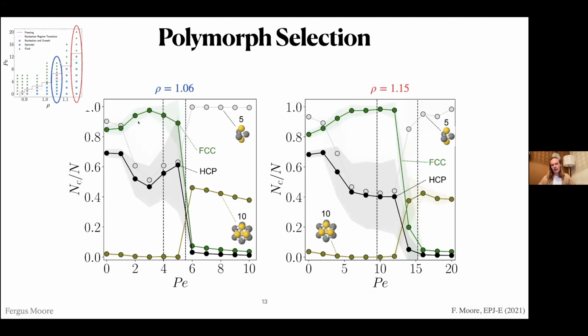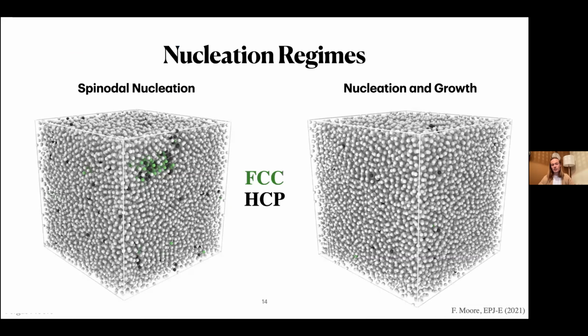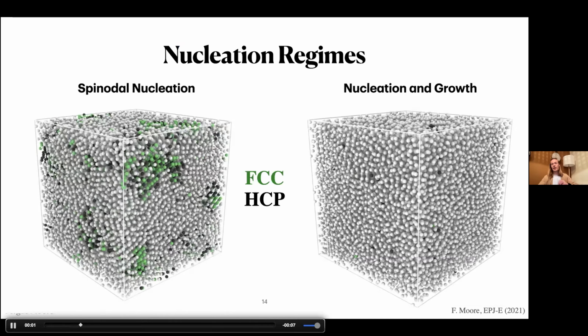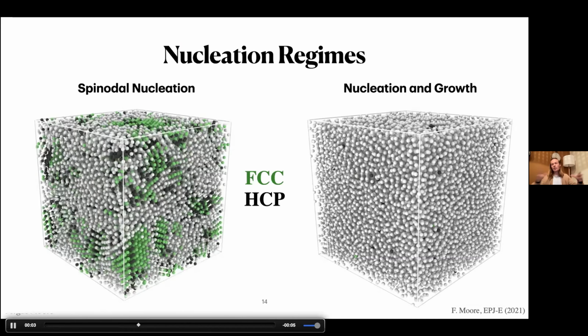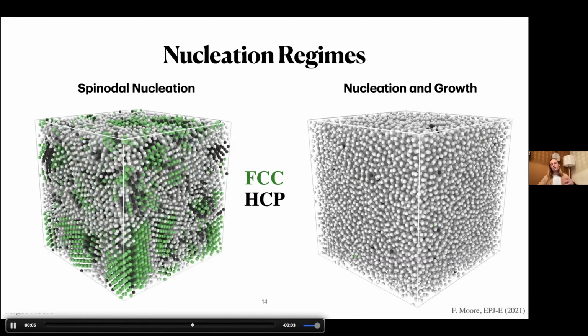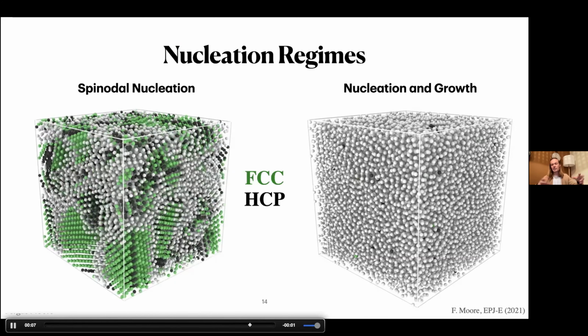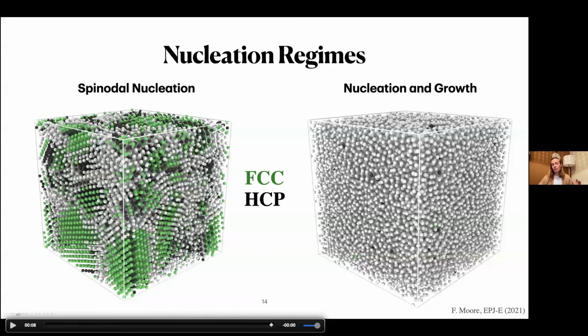So to the left of this line, we're going to be looking at spinodal nucleation. And in between here, when you have a slightly different polymorph selection, we have nucleation and growth. I'm going to get into the differences between those two now. Spinodal nucleation is a spontaneous phase change, multiple nucleation events. You see the crystal grows from different areas of the simulation at once, and there's a lot of coarse grain boundaries when it happens this way.